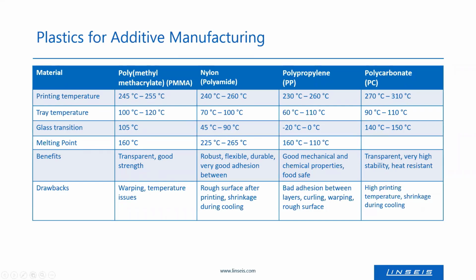PMMA is often used as a replacement for glass since it's transparent, has a good strength, and is shatterproof. But the problem with PMMA is that it's not that easy to print because it can get opaque really easily depending on the temperature. So here the temperature management is also very crucial. And warping is also a problem with PMMA. What this is, I will also show you a few slides later.